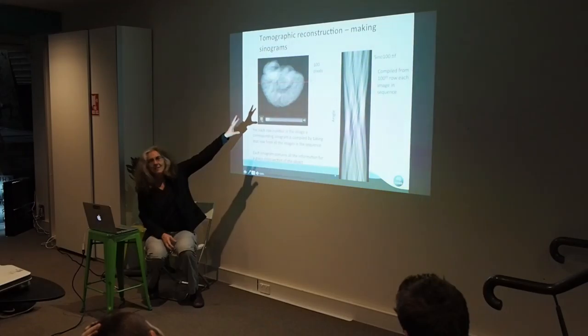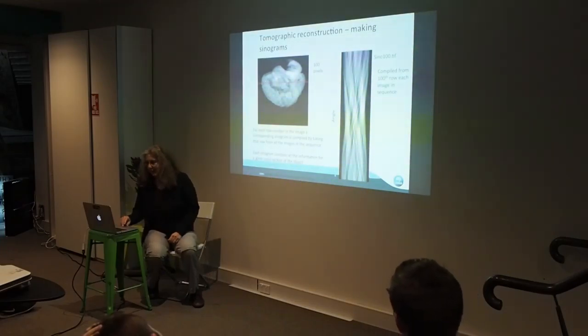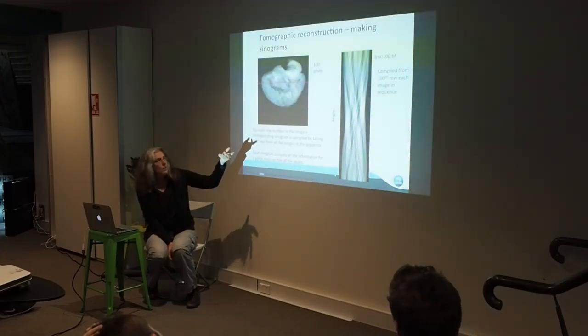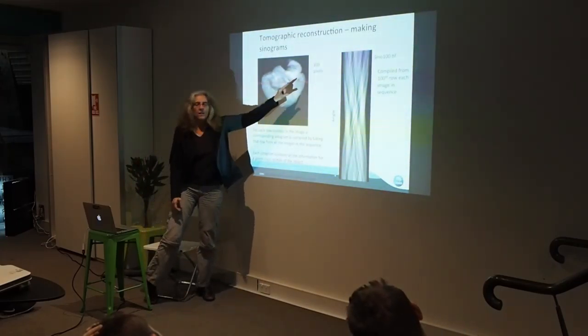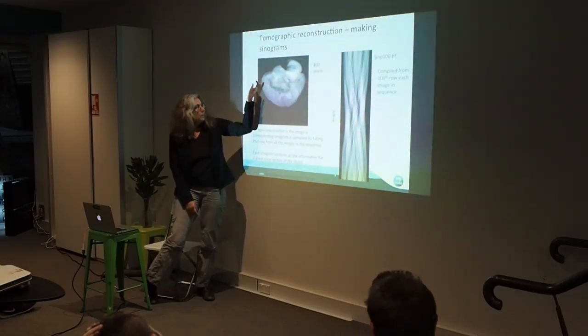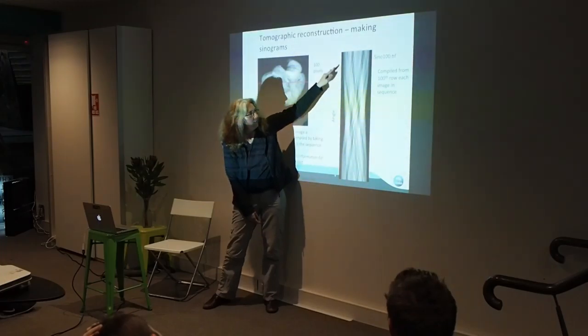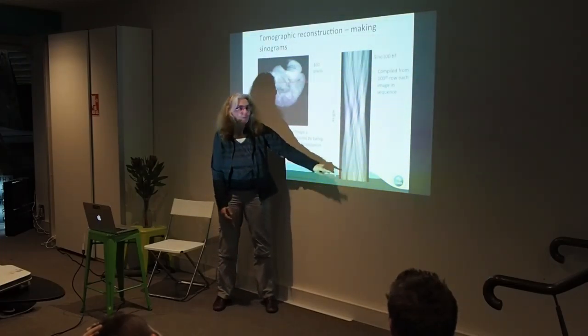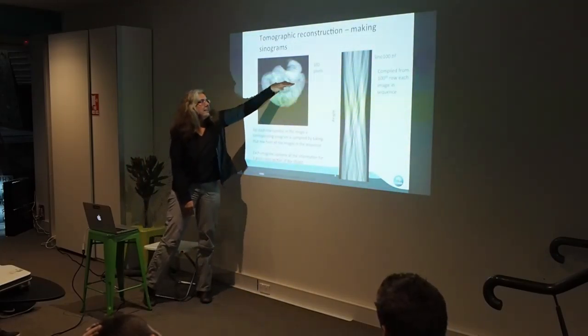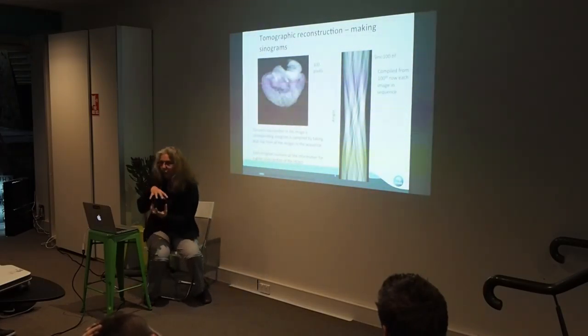This is like a data set — actually a synthetic data set, a pretend data set. You'll see that the contrast is being inverted, which is just something we have to do so that the mathematics works out. We're taking a bunch of images as it rotates. If you take one line of this image, one layer like that, as it rotates and you take that layer and plot that line for each angular position, you get a kind of weird image called a sinogram.